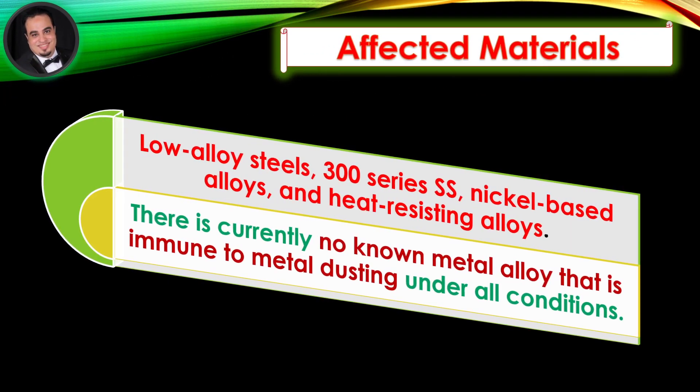Affected materials include low alloy steels, 300 series stainless steel, nickel-based alloys, and heat-resisting alloys. There is currently no known metal alloy that is immune to metal dusting under all conditions.